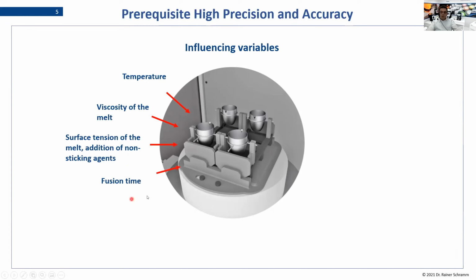The fusion time is very important, and especially if we are looking at volatile components like sulfur or halogens, then temperature and time become very important, because they will influence how volatile your components are and how much you lose during the fusion. And only if you can keep both very constant, then it's no problem, for example, to analyze chlorine in fusion. Another very important point is the temperature distribution, so that every crucible sees the same temperature, so that you don't have different results depending on where your sample has been during the fusion.